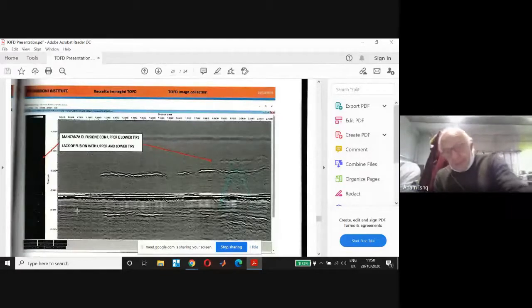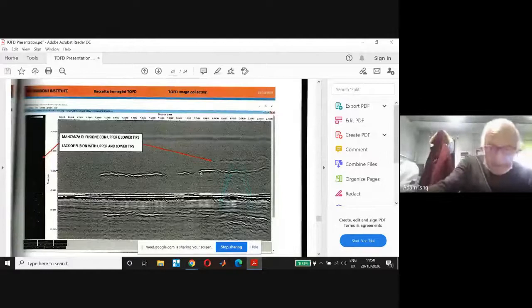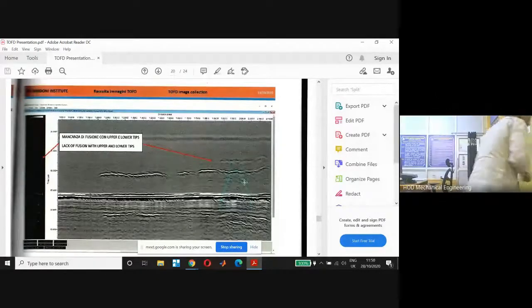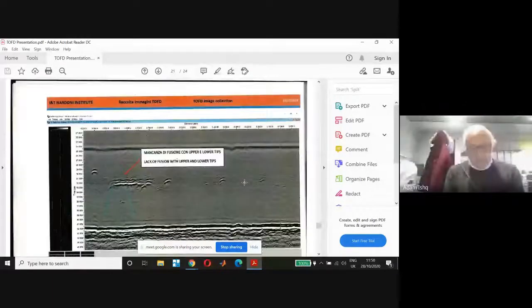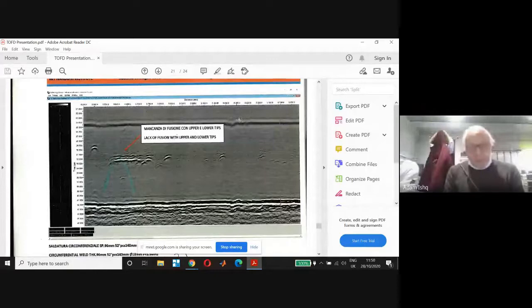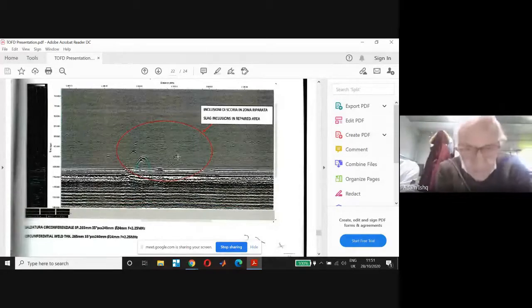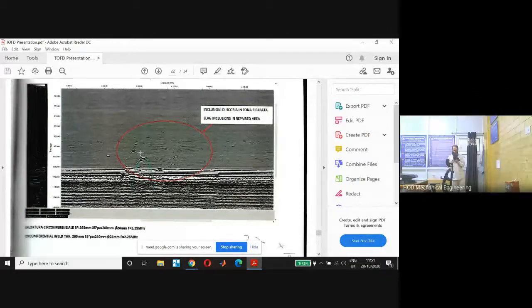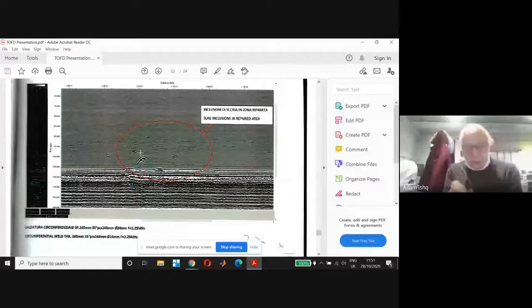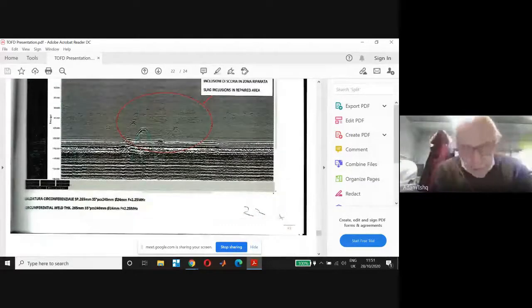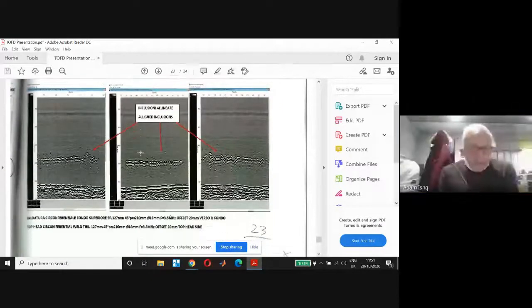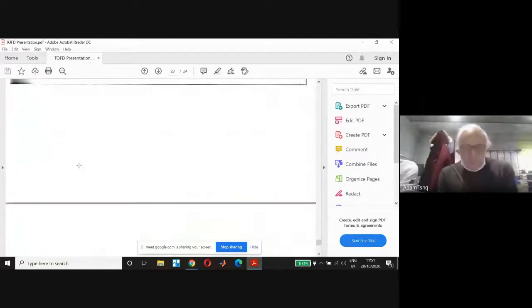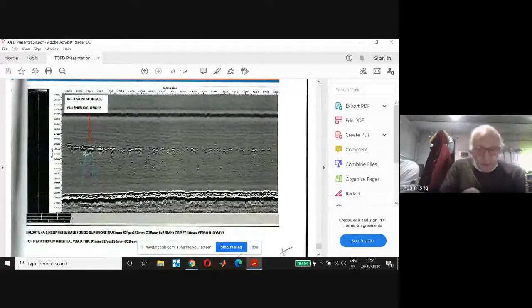Here you see the thickness. You have the lateral wave up and down, and you have the back wall. Again, you see lack of fusion with some inclusions. Linear is always lack of fusion. And also you can measure very high. But at this smaller thickness, you see a very small inclusion. When you see this arc, that means that the defect is very short. So you see an arc, a small inclusion. Again here, these are again lack of fusion.